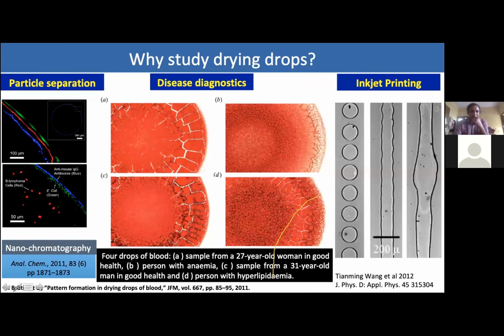You also see an example where this technique has been used in particle separation. What you're looking at at the top is the edge of the evaporated drop, and if you zoom in, you see three distinct colored lines: green, red, and blue. These lines correspond to particles of different sizes, and they appear different colors because they're fluorescently labeled. If you have a mixture of three different sizes in an evaporating fluid, the smallest particles go to the farthest edge of the drop, followed by the medium size, followed by the largest size. So one could start with a droplet that contains particles of different sizes and separate them by using this principle.